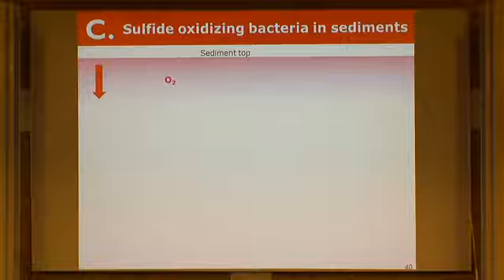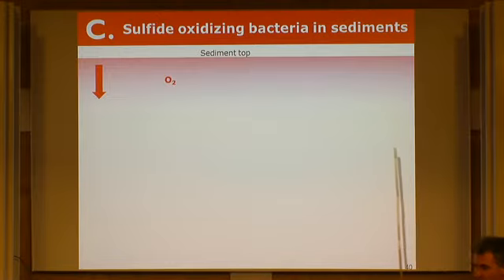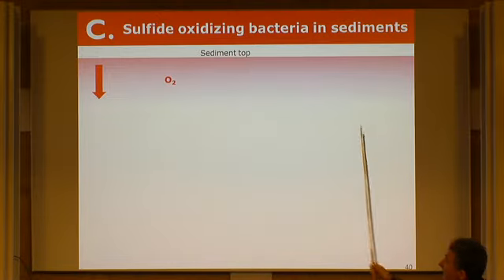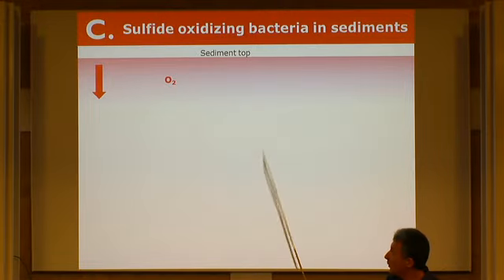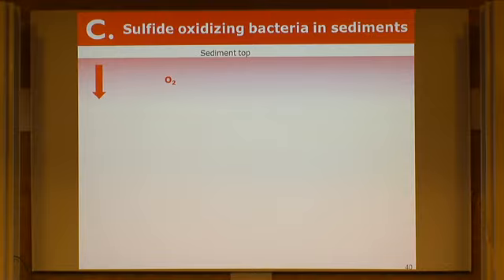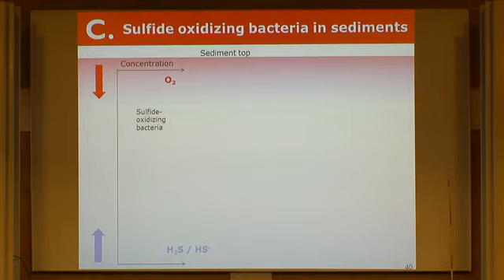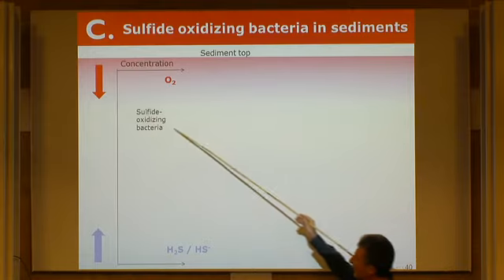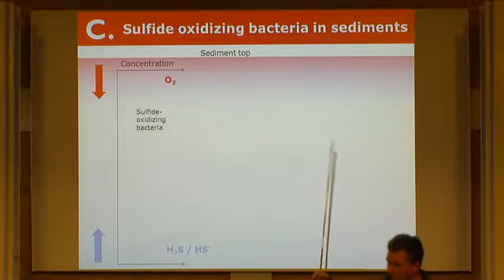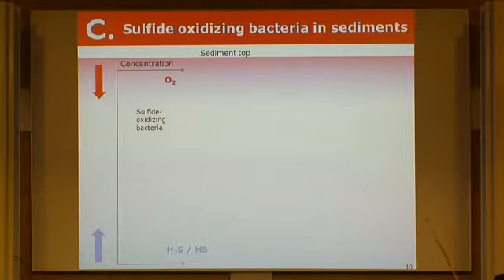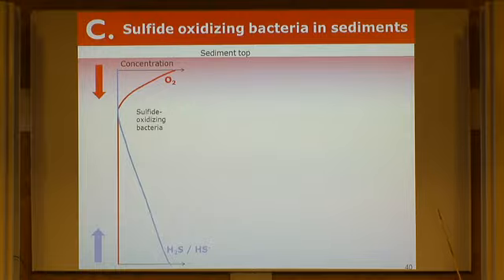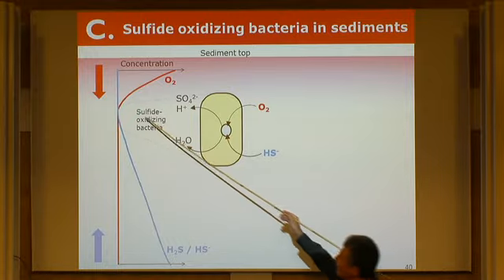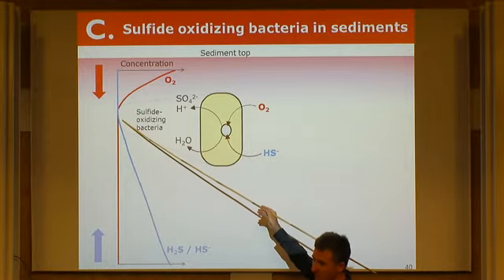Sulfide oxidizing bacteria. You know the papers from Nielsen, Denmark, Aarhus. We have now kind of a model for their system. So imagine a sediment now. Oxygen coming from the top. This is the aerobic part, red. Sulfide coming from the bottom of this sediment. So you would have typically sulfide oxidizing bacteria somewhere in the middle where the sulfide meets the oxygen. So an oxygen gradient and a sulfide gradient, and the sulfide oxidizers should live happily at this place.